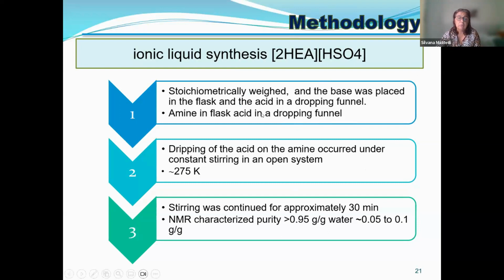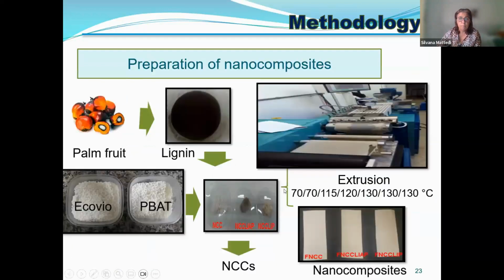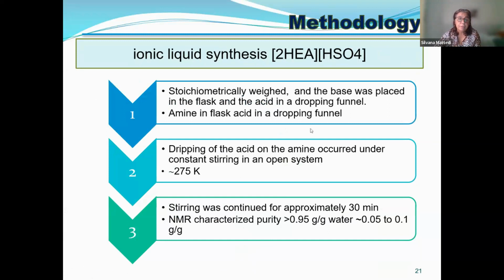The difference from the traditional synthesis is that we really need to use a very low temperature and a very careful dripping of the acid onto the amine. We use 8 degrees Celsius. Oh, sorry, 2 degrees Celsius. It's a very low temperature because if you put the amine directly in the acid, it's a very quick reaction and it can explode. We have seen in the literature that what they normally do is to put in a lot of water. As we don't need so much water, we prefer to do it concentrated at low temperature.